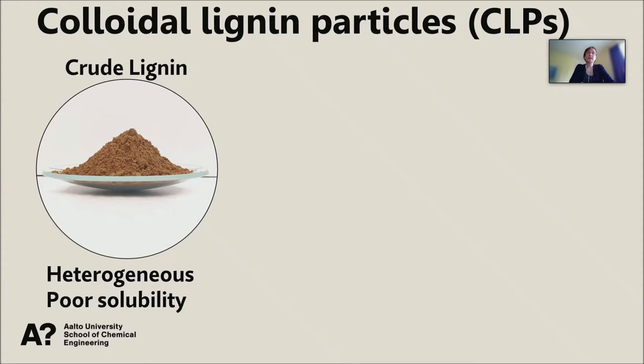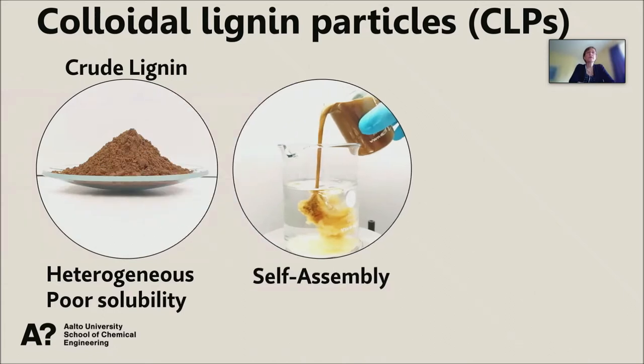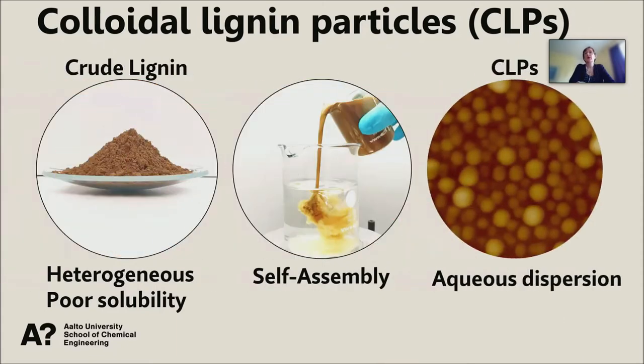It usually has quite poor solubility, especially the lignin that you get from the bioethanol industry, which is very condensed and very difficult to solubilize. So our approach was to take this heterogeneous material, solubilize it in an organic solvent, and then just by pouring this solution into water, we form spontaneously spherical colloidal lignin particles.